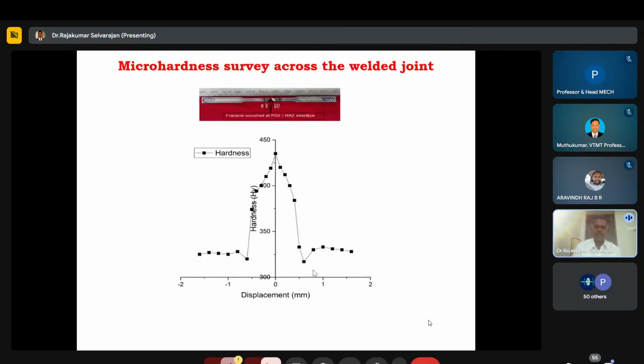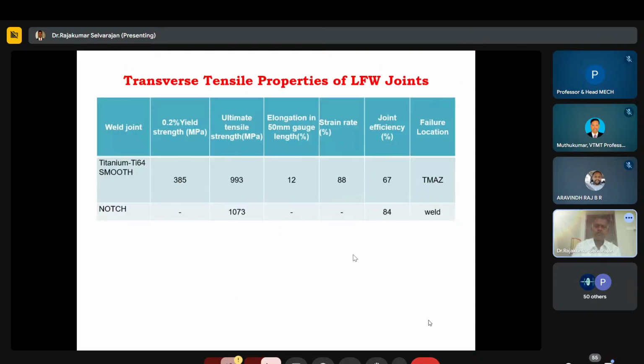So you can take the hardness through the weld hardness survey across the weld region. You can see that the weld center gives a maximum hardness of 450, and the TMAZ region gives 320 or 330. And then the base metal gives less than 330 or 340. So this is the table that was recorded.